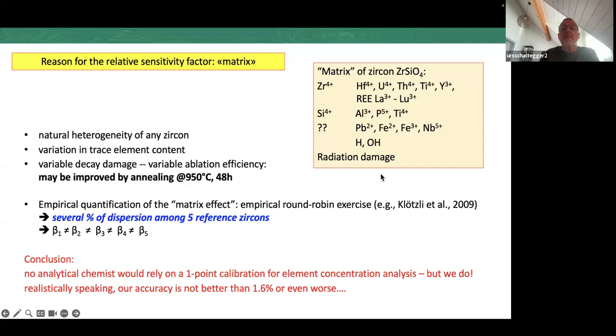And then in addition is the radiation damage. So that means any natural zircon is heterogeneous, has a natural variation of trace elements. And the variable decay damage actually leads to a variable ablation efficiency. So this is actually the easiest not to overcome, but to improve. When we anneal our zircons dry in a furnace at 950 degrees, we get rid of part of this analytical scatter due to variable ablation efficiency due to radiation damage.